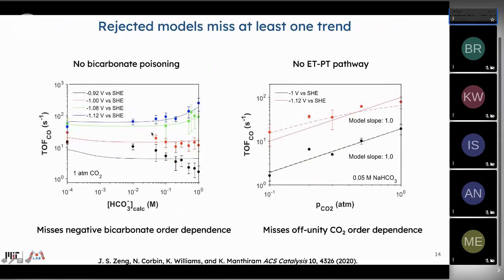We can reject other models. So if, for instance, we don't have bicarbonate poisoning, it's not possible to see the negative orders. You can see how the lines and the points disagree when there's no bicarbonate poisoning implemented. If there's no ET-PT pathway, in other words, a pathway in which an electron transfer precedes a proton transfer, we can no longer account for the non-unity orders in terms of the CO2 order dependence.